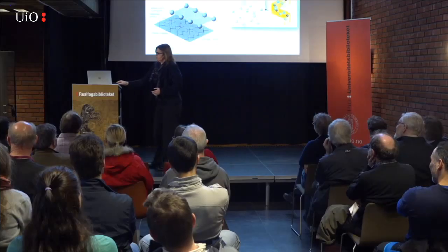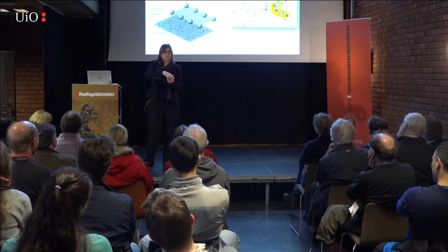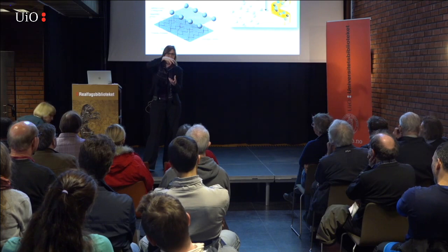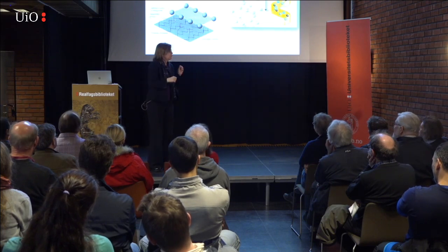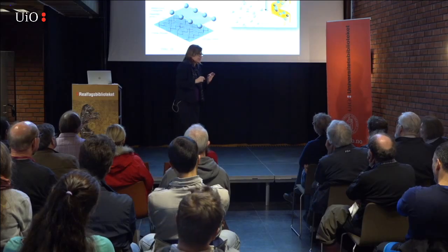So basically, if you've seen geologic aragonite, it grows as this pillar, this hexagonal pillar. But when I showed you how it grew as an abalone, it grew these thin tablets. It's because it grows these thin tablets that are laterally offset, and it gives us this really tough structure. So the proteins can actually control not only which crystallographic structure is grown, but also what orientation is grown, and make certain axes longer and certain axes shorter.